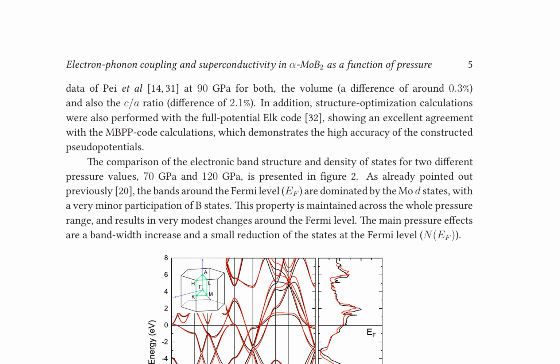Data from Pei et al. at 90 gigapascals reveals a 0.3% difference in volume and a 2.1% difference in the c/a ratio, demonstrating high accuracy through structure optimization calculations using the ELK code.